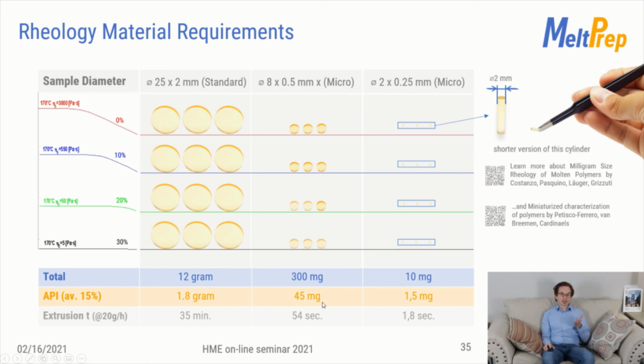Imagine operating an extruder at the lowest throughput that you can find, let's say 20 grams per hour. You have less than a minute to find your operating parameters before you wasted the amount you would need for rheology. If this is still too much, even smaller sizes are available, but they also require experienced rheologists to perform the measurement. The material requirement can be as little as 10 milligram, corresponding to extrusion times of a few seconds.